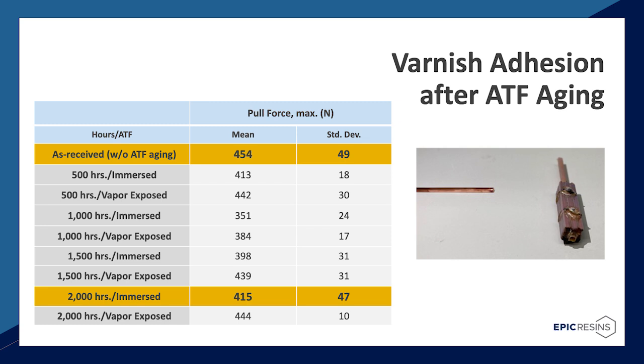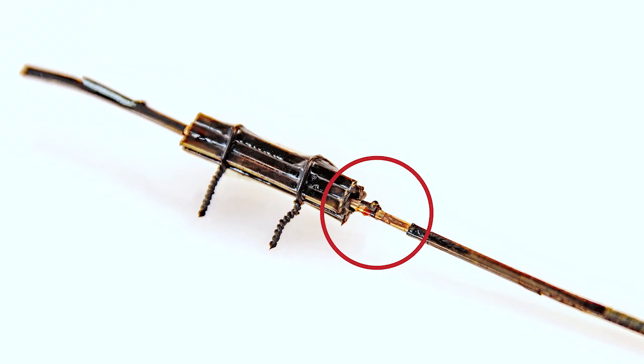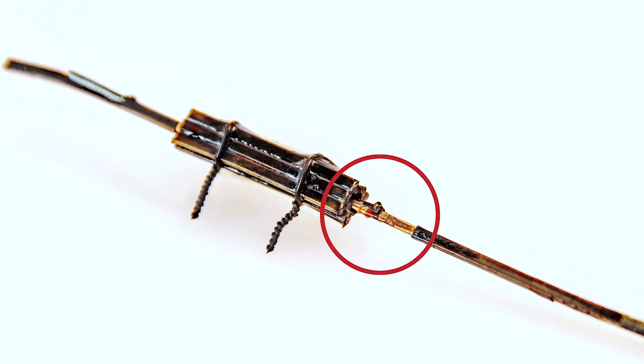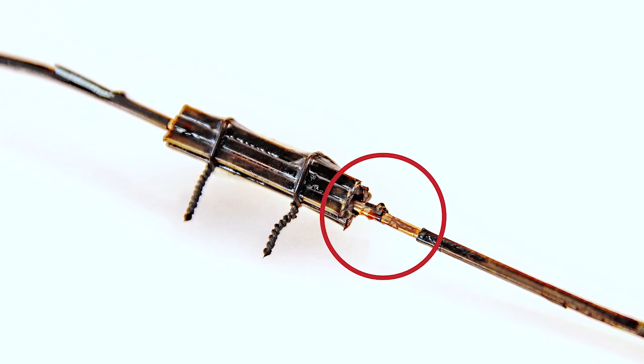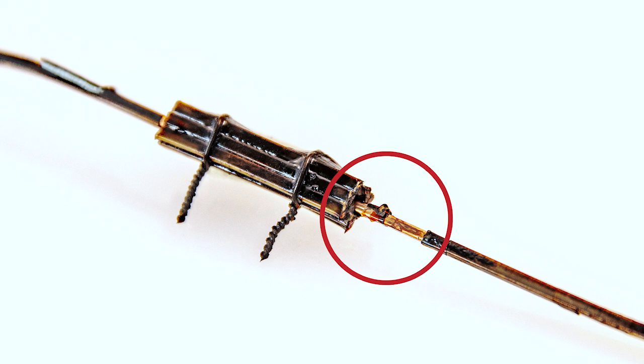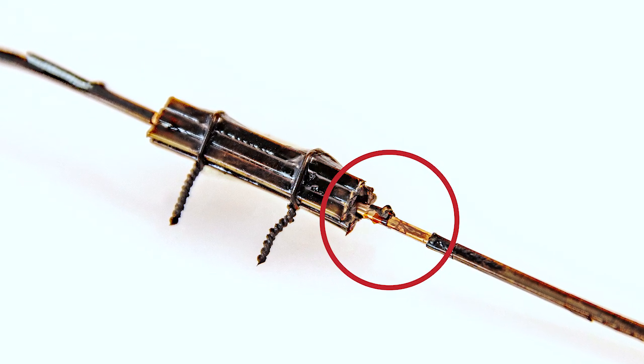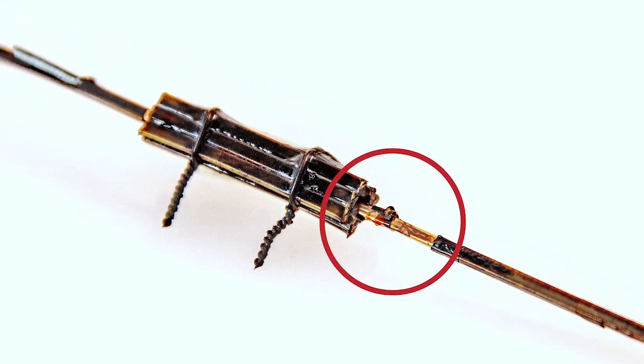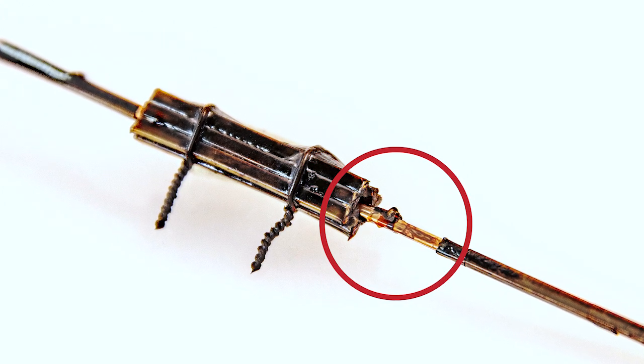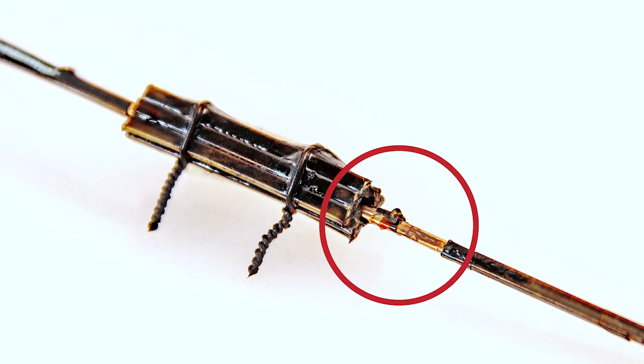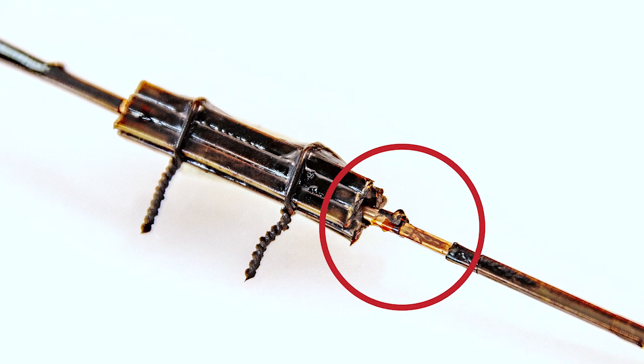From the data collected, you can see that after 2000 hours at 150 C exposure immersed in ATF, over 91% of the original adhesion was maintained, and over 97% was maintained for ATF vapor exposure. Additionally, during analysis, separation took place between the PEEK coating and the copper wire, while the bond between E240 insulation and PEEK coating remained intact.